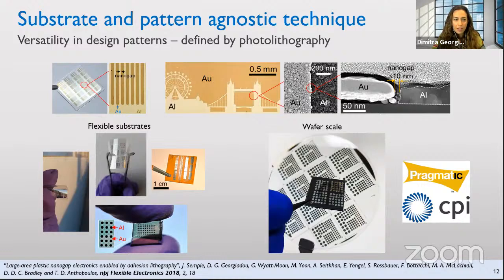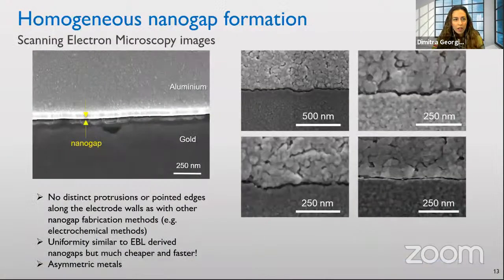We have also applied this technique on flexible substrates, PET, PEN, polyimides. Also, we have upscaled to a wafer scale. So from the lab scale substrates, we can also fabricate wafer scales and then cut them to the desired size to do our measurements. The gap is quite homogeneous.